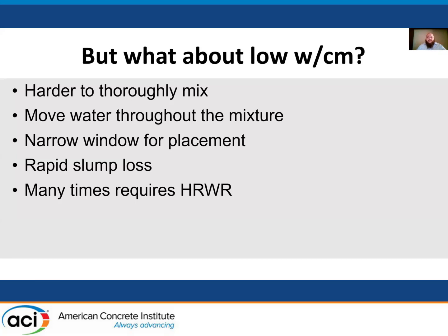The cement starts clumping up and balling up everywhere, and all of a sudden you think that you have a coarse aggregate or something in your mix when you really don't. You have a lot of cementitious, you have fine aggregate, and so you really got to mix it up really well. And once all that water is distributed, it's crazy how it changes into this SCC that we think of.